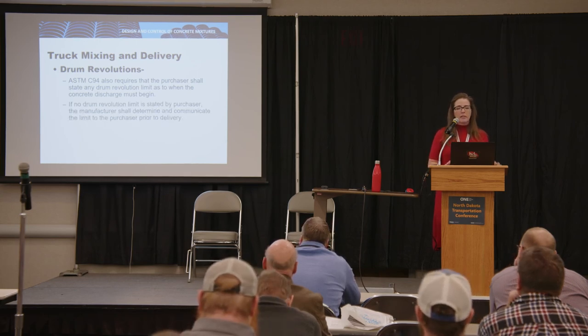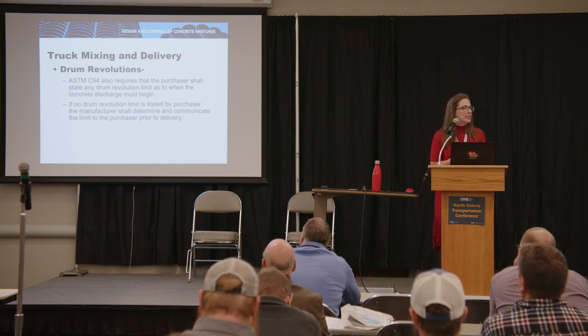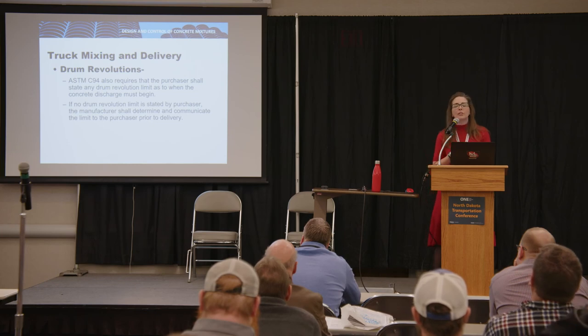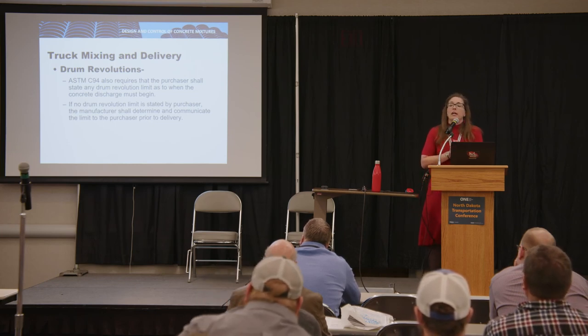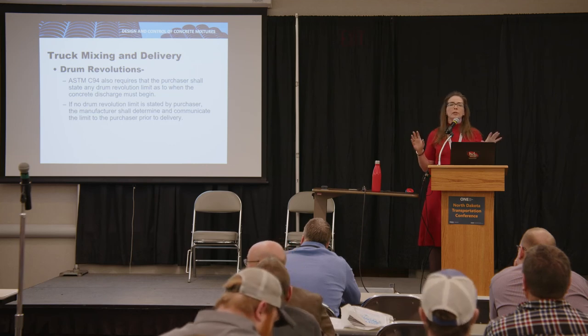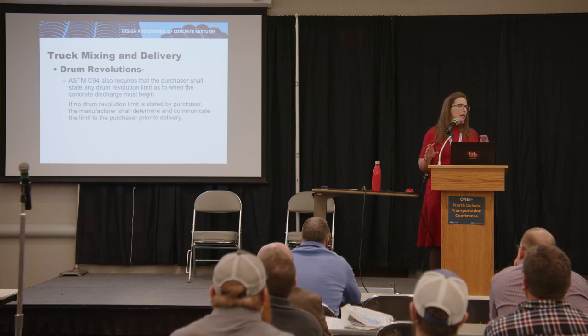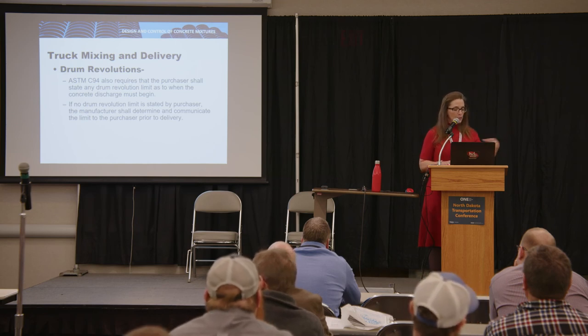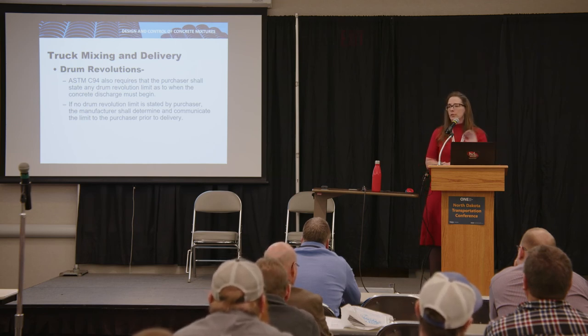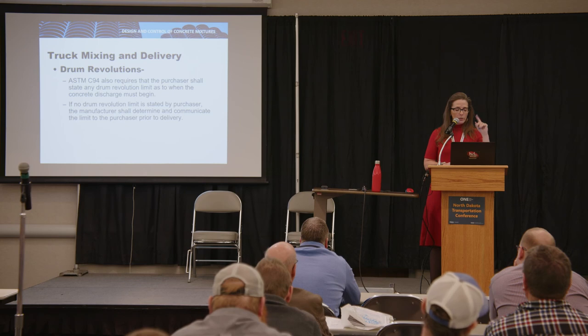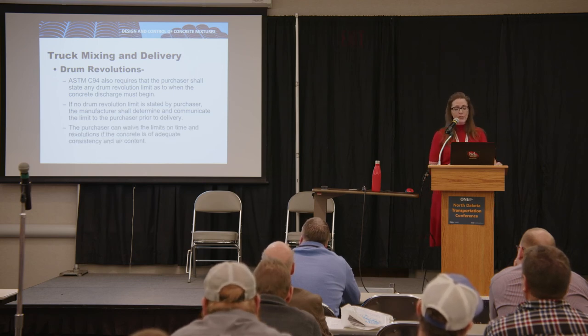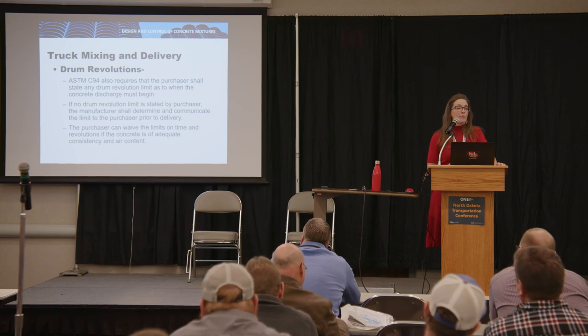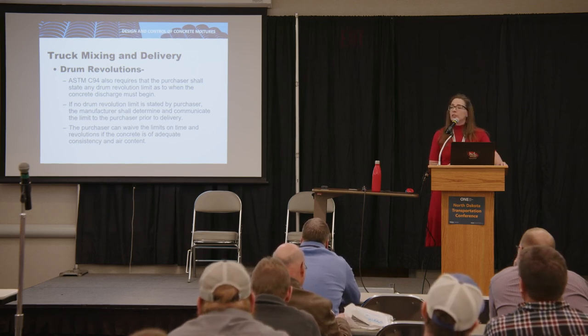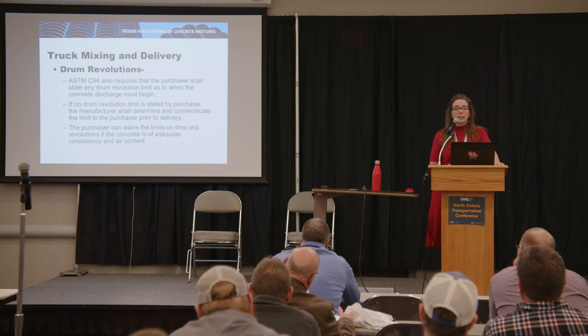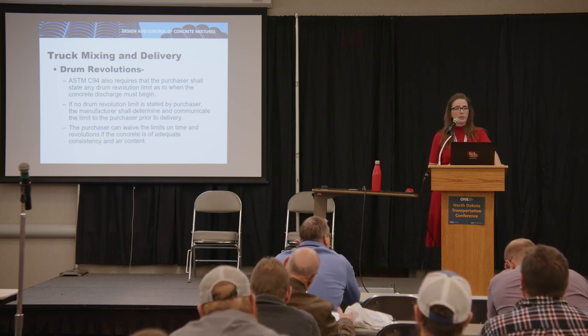So with this, we let go of the 300 because it was based on a specific friable aggregate that they feel is rarely used, and they did a lot of research at NRMCA and others, and this was the least of my worries. What cracks me up the most are people that actually thought 300 revolutions was tied to 90 minutes, because there's lots of drums that don't move. So this is not something I will lose sleep over. I would like to talk long and hard about that time limit and what your expectations are. But purchasers can waive these limits, so as the owner's reps think about it, it doesn't have to be 90. Just tell them what you really want and be very clear on it, and just realize you're going to have to pay for it too if you ask for it to set quicker or if you ask for it to last longer.